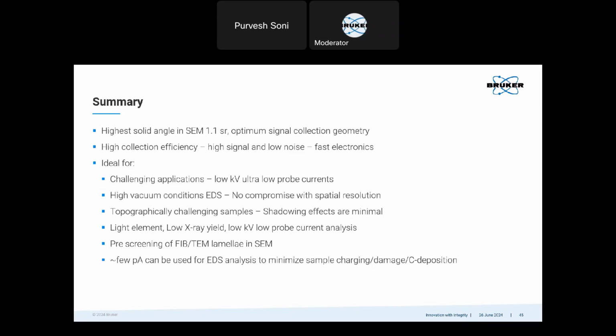And this detector is ideal for challenging samples where you really need low kV and very low probe currents, and still get very high resolution, and maybe also minimize charging for, let's say, beam sensitive samples. Because of the low probe currents, you can still use high vacuum conditions, so you don't compromise on spatial resolution when you use the flat quad. And with the four segment design annularly placed, you have no problems if there are topographic samples or shadowing samples. I also showed that you could detect as low as boron with this detector.